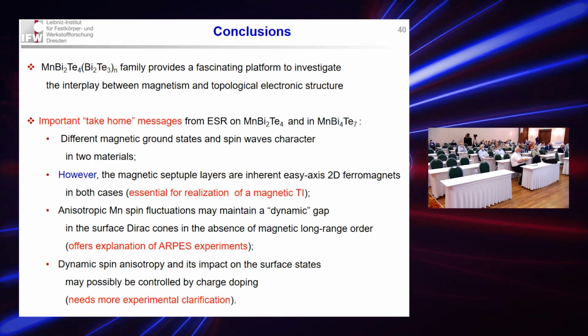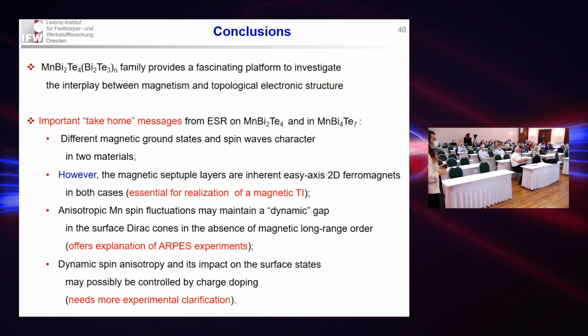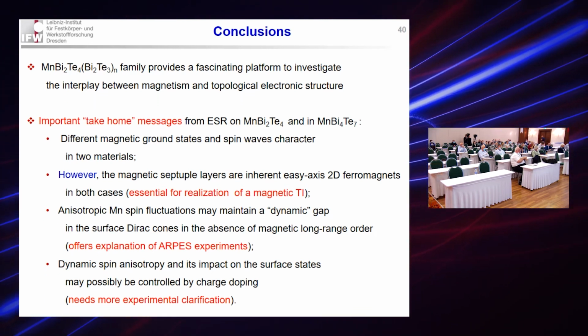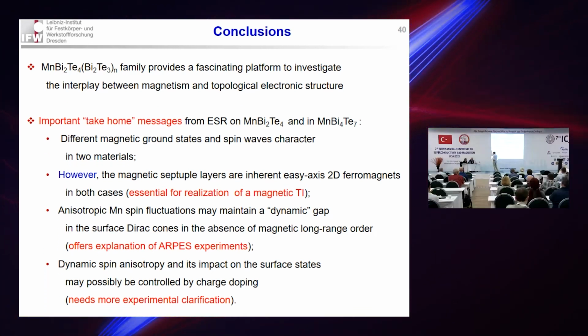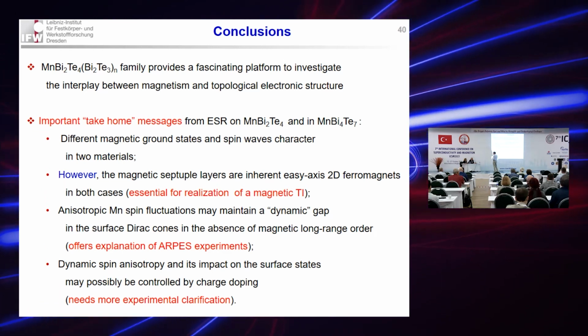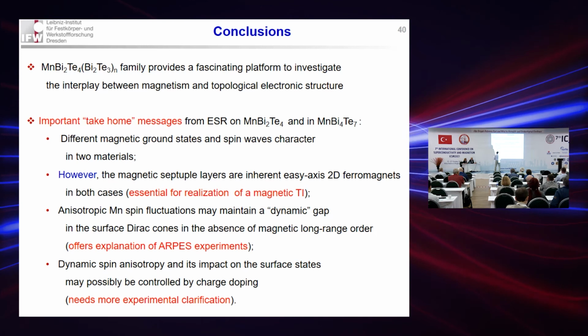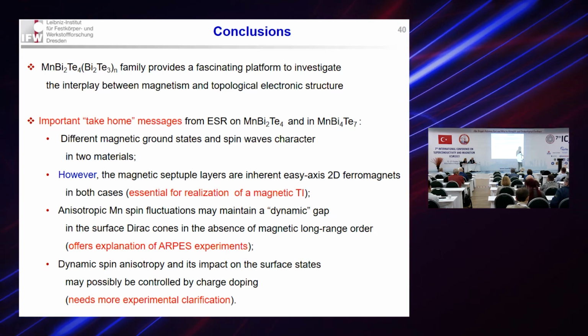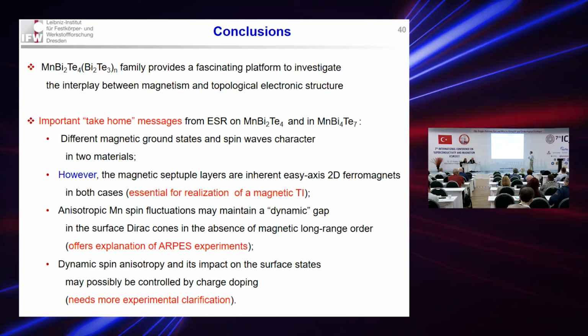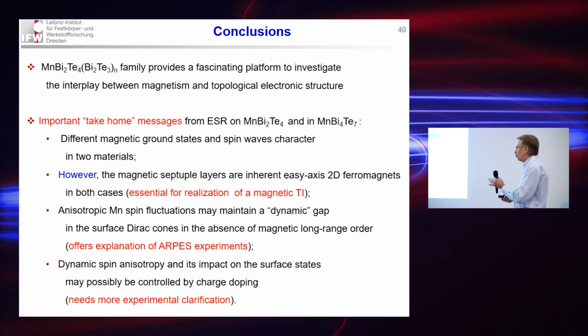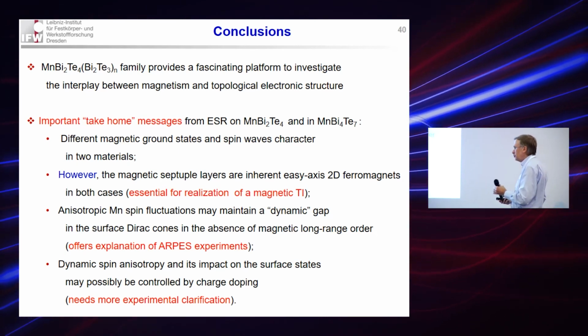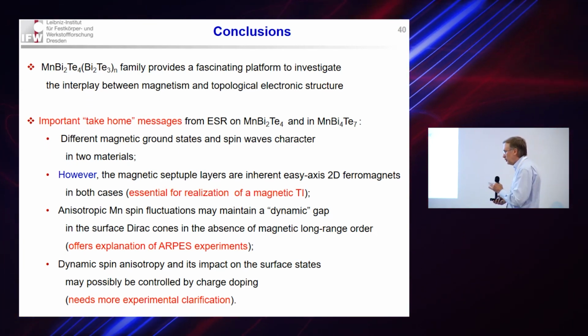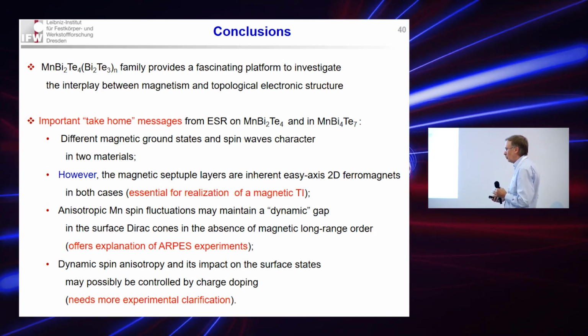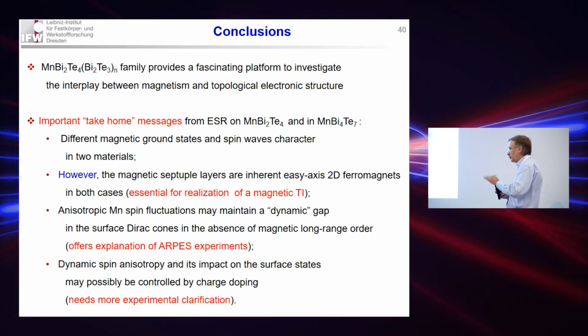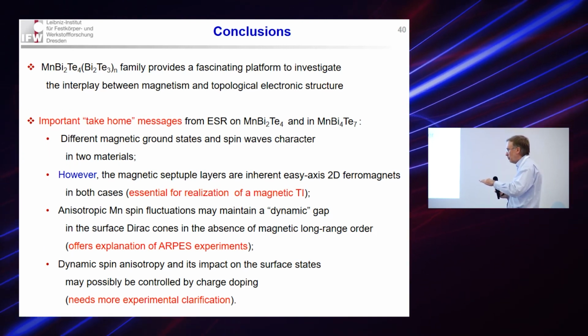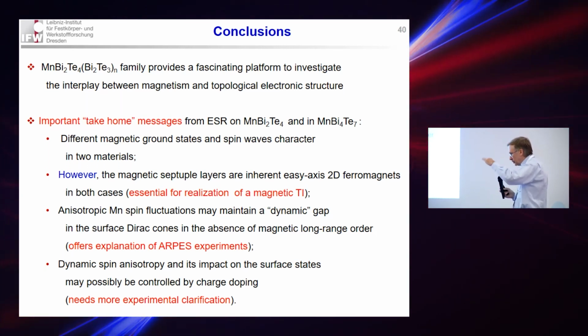Professor Kataev, I have a question. When you compare your results with experimental data, is there any size dependence of the properties in topological insulators? Size of the measured samples? Yeah. So these are not our own experiments, but experiments which I mentioned. These are measurements of the quantum Hall effect in thin flakes of manganese bismuth telluride 1 to 4. And indeed, they observed that this effect increases with decreasing number of layers.